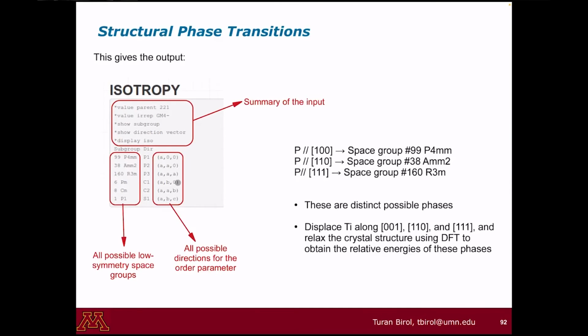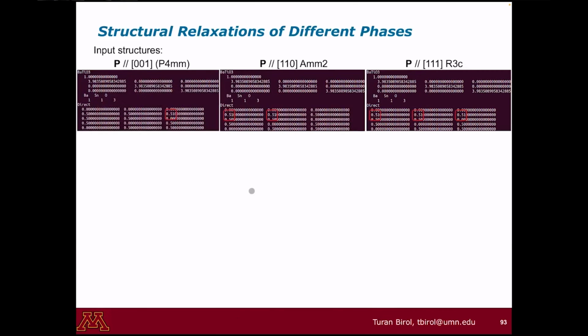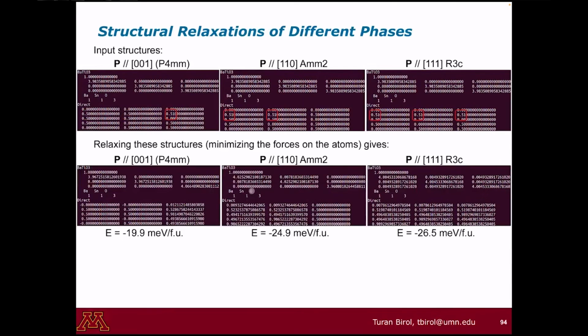For example, when you have a displacement along x and y by equal amounts, you end up with this space group AMM2. But if they are by unequal amounts, you end up with a much lower symmetry space group, just P. And this A is like a vector displacement of all the atoms, by different amounts. If I displaced all the atoms by some vector, if I do it in X, I should do the same in Y. Correct. And when you are trying to take into account all the atoms at the same time, things get a bit tricky.